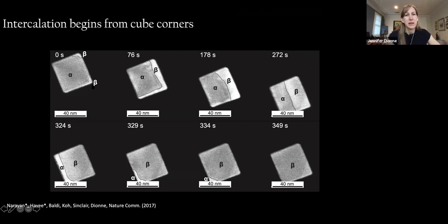So we see that the beta phase actually starts from the corners of the cubes, and then it appears as if some of the surfaces kind of get wet with hydrogen. So we have this subsurface loading, or what appears to be subsurface loading. The beta phase eventually stabilizes along one of the 100 fronts, which is one of the lower energy configurations for this alpha-beta phase coexistence when you're not in equilibrium. That hydrogenated phase then continues to move with this straight or flat phase front across the nanoparticle until eventually the alpha phase is pushed out again through another corner of the cube.